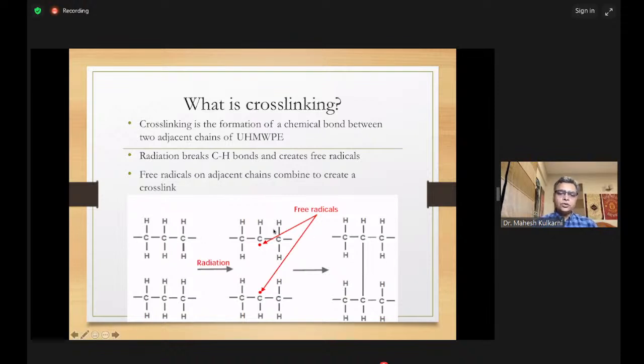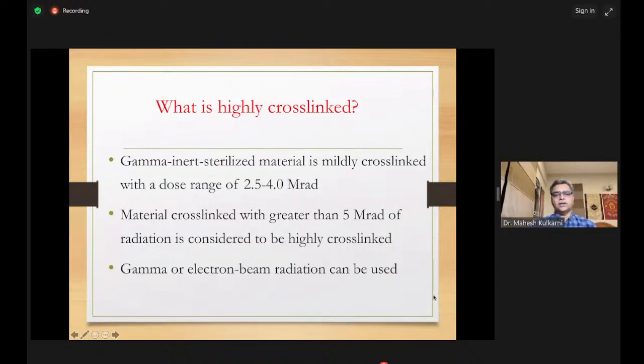So you get 2 chains of polythene, and with a reaction, either with gamma irradiation, you can create cross-linking between these 2 chains. And once you form cross-linking, there are bonds between these 2 molecules, and that produces a highly cross-linked polythene. But at the same time, you create some free radicals. We'll talk about that as well.